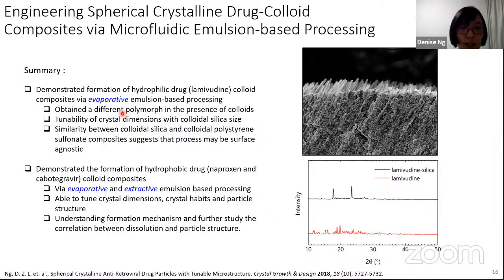And we observed that actually we can obtain a different polymorph in the presence of colloids. And we can actually tune the crystal cross-sectional dimensions just by changing the colloidal silica sizes. And the similarity in outcomes between the colloidal silica and colloidal polystyrene composites suggests that this process may actually be surface agnostic. We then move on to extend and generalize our technique for hydrophobic drugs. And we demonstrate it for both evaporative and extractive emulsion-based processing, where we are also able to actually tune the crystal dimensions, crystal habits, and particle structure.